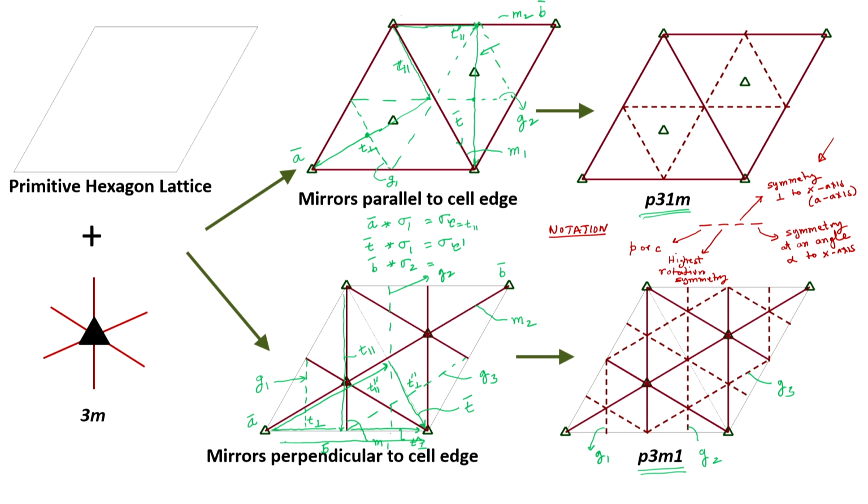So, in this case the orientation of the point group was such that the mirrors are perpendicular to both in fact the x and the y axis. So, mirror will go as the third symbol, and there is no other symmetry to put on the fourth symbol. So, it becomes P3M1. So, we have these two plane groups done.